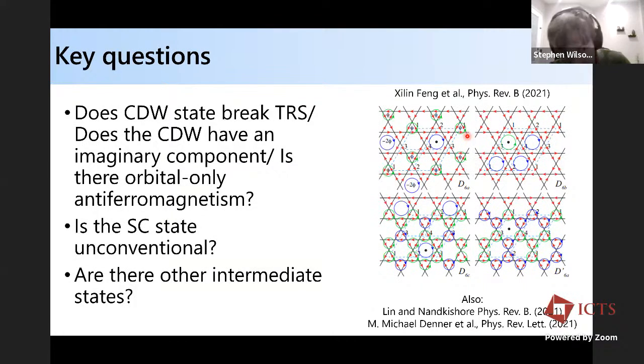Okay, so the key question is whether any of this exotic physics predicted from nested Van Hove points in a Kagome lattice really manifests in these materials. One of the questions explored by the community is: does the charge density wave state break time reversal symmetry? Another way of saying it, does the charge density wave have an imaginary component, or is there some orbital-only antiferromagnetism present in these systems? The second question is whether the superconducting state born from this charge density wave phase is unconventional. And the third is whether there are any other intermediate states or instabilities as you go from the primary charge density wave instability all the way down to the superconducting phase.